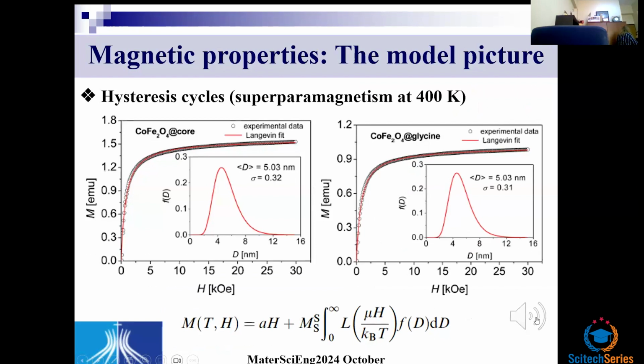This slide shows typical magnetic properties of the uncoated and surface-coated cobalt ferrite nanoparticles. So it shows the hysteresis cycle at 400 K. On the left-hand side is the uncoated nanoparticles, which means exactly the core of cobalt ferrite. On the right-hand side, we have the hysteresis cycle, also at 400 K, recorded from the sample which was surface coated with the shortest amino acid, which is the glycine.